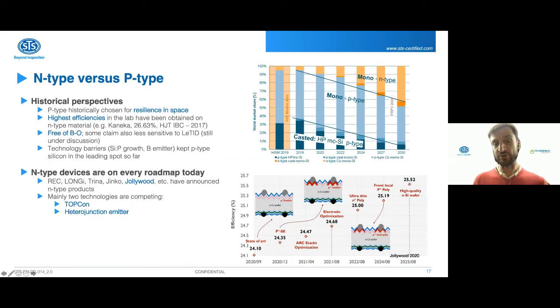Last historic trend that I want to talk to you about is N-type versus P-type, also very, very historic. This time P-type got a head start, and mostly for reasons of better resilience for space application. However, the highest efficiency most of them are done on N-type when you look at what happened. And in fact, today the top efficiency, the record efficiency held by Kaneka is indeed on N-type material. N-type is also free of boron oxygen, and it is even claimed that it's less sensitive to LeTID, but this is still a little bit under discussion.